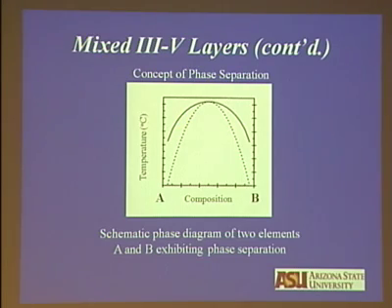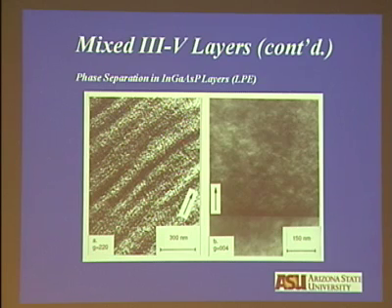Now, the next is you're going to look at how phase separation manifests itself in the materials. You are looking at indium gallium arsenide phosphide layers grown by liquid phase epitaxy. What do you see? The growth was on the 001 plane of indium phosphide. The composition that we used, we grew the materials ourselves, emits at 1.33 micrometer. That's the wavelength used by lightwave communication systems. You look in the plan view, you image with the 220 reflection, and what you see is a speckle structure on a very, very fine scale.